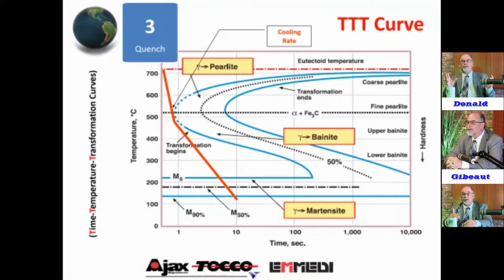And I'll address that here in a minute. But the bottom line is you start getting out of this window at this MS point, and you start getting into a differential of grain, mixture of pearlite, bainite with your targeted martensite metallurgical properties. So the desired, and like we said, we typically get 95+% martensite with our uniform heat, which is required, but the quench is where the magic is made here.